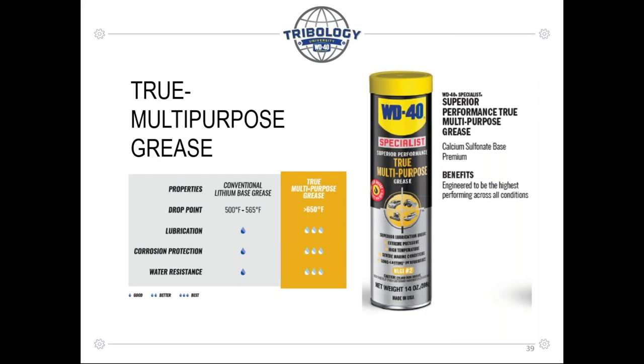When that drop of oil comes out, that's the rating. You can see conventional lithium greases, 565 is actually quite high. They typically range about 500 to 550 degrees Fahrenheit. Calcium sulfonates will afford a higher drop point. So we actually go over 650 degrees Fahrenheit. 650 is actually the highest you can go. So we're very proud of the fact that we developed something that has superior and excellent thermal stability. And as I mentioned, calcium sulfonates are better at water resistance and corrosion protection as well.